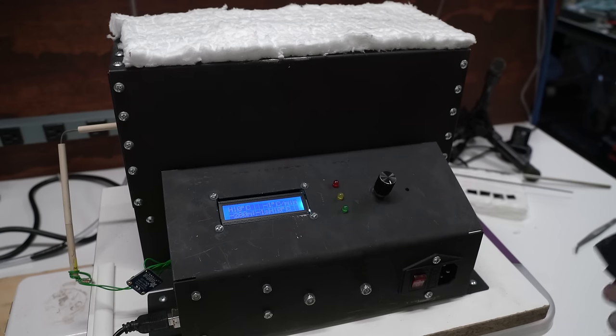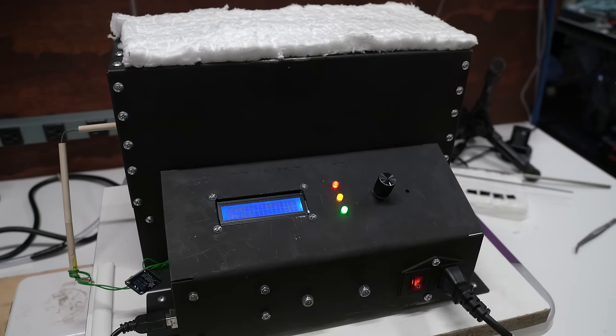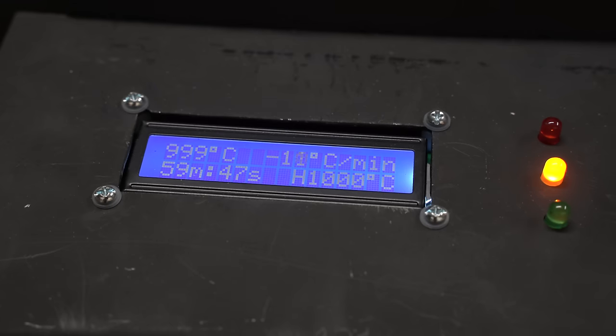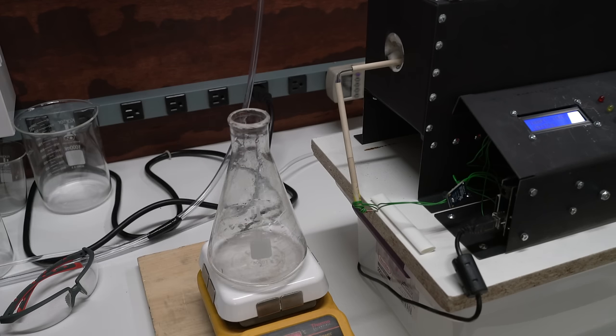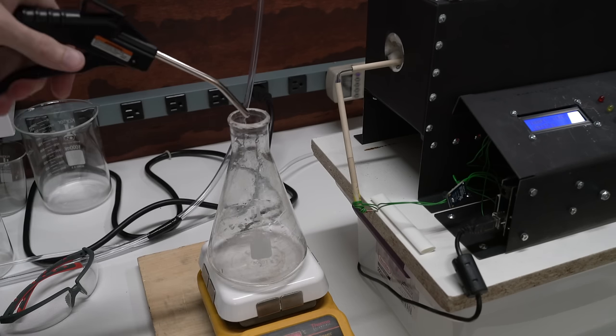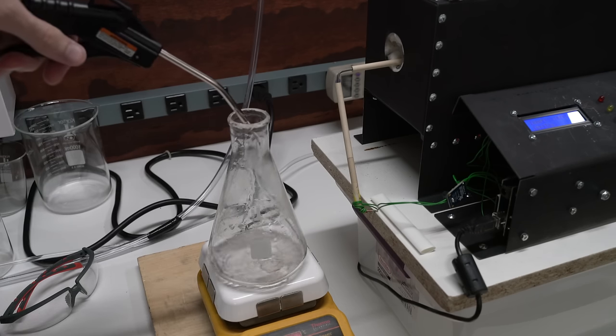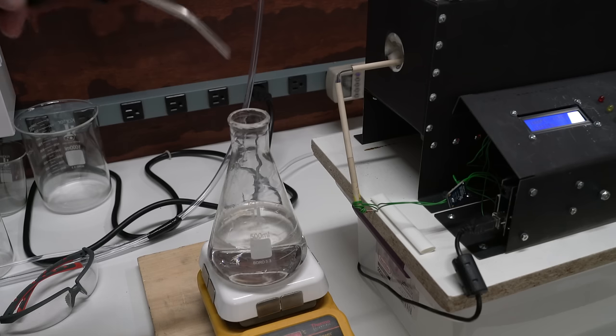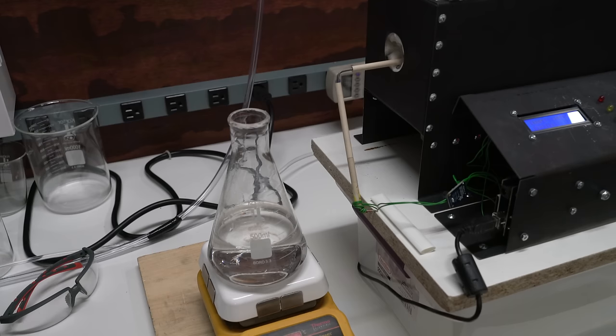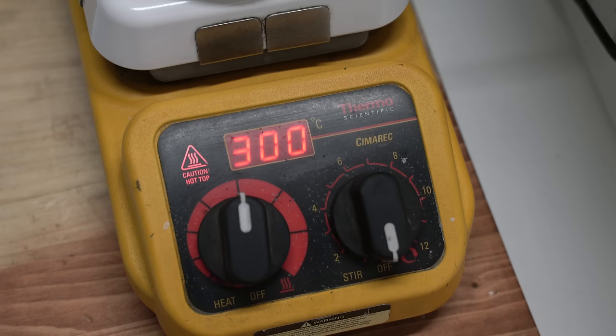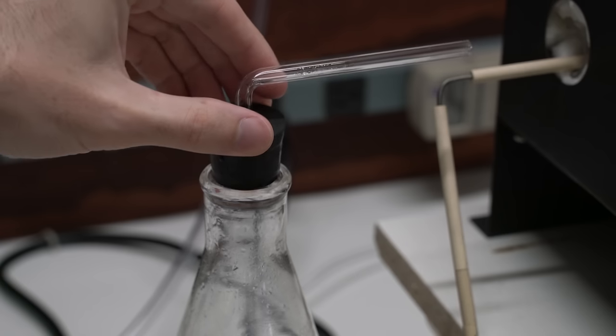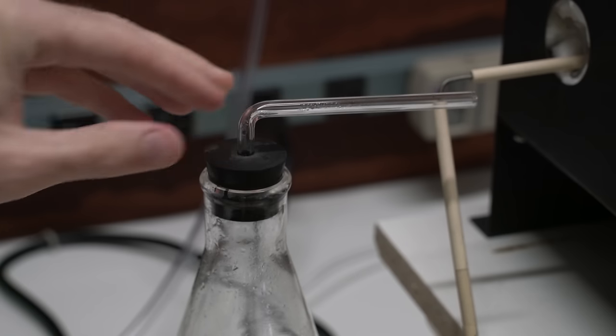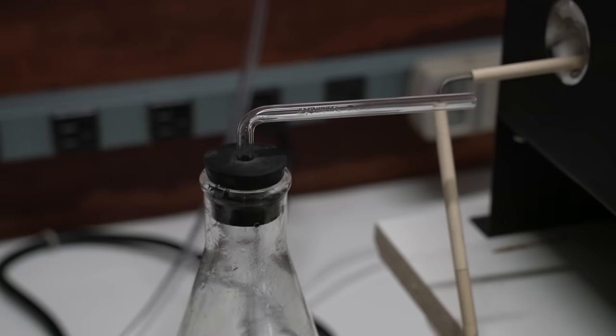I'm using the tube furnace I built in the last video to do this oxidation. The furnace is set to 1000 degrees Celsius. We need a source of steam, which is going to be from this Erlenmeyer flask. I've filled it with a couple hundred milliliters of water, which should be enough for a couple hours at least. I'm setting the hot plate to medium, which is a gentle simmer. I've added a stopper and a right angle glass tube to redirect the steam so that it can be fed into the tube furnace.